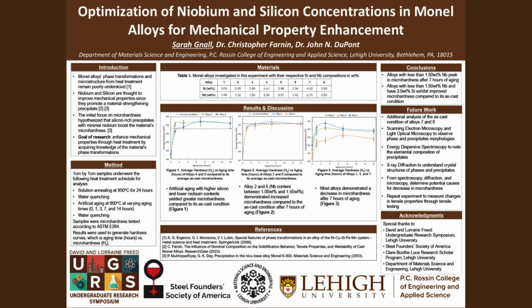First, the material is heated at a specific temperature and time to produce a single phase present in its microstructure. This is known as solution annealing. The material is then quenched, which seals that single phase being present. From there, the material is heated to a different temperature and time to grow a precipitate that will improve material properties. This is known as artificial aging. Then the material is quenched again to seal those precipitates being present. The parameters in this process are temperature and time, which are both material-dependent variables.